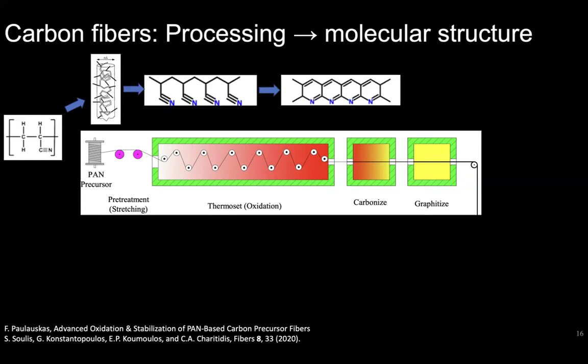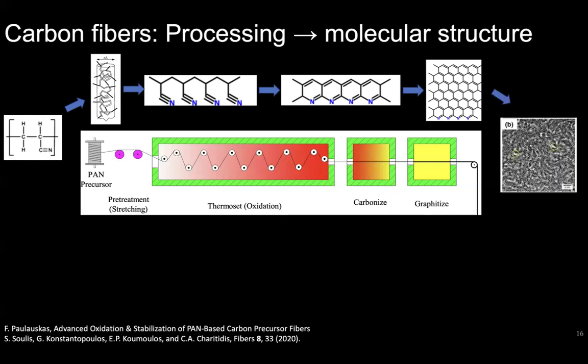And then you go through a process called oxidation and stabilization, where you make it react to create these cycles, these ladder type structures that you see over there that can withstand the high temperatures that you need for the last step, which is carbonization. Okay, so then you take these ladder structures, you make this into these graphitic sheets, and that's what a carbon fiber looks like. So if you look at a carbon fiber in a cross section, you have a lot of these graphitic sheets all bent